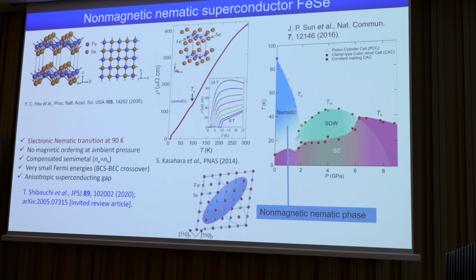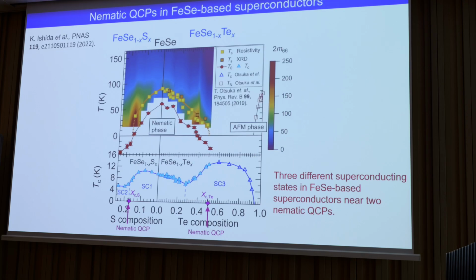But we want to try to understand the interplay between the nematicity and superconductivity. Our next strategy is to use chemical pressure, so we can substitute the selenium site with the isovalent sulfur or tellurium. In this phase diagram we have iron selenium here, with sulfur substitution on the left-hand side and tellurium substitution on the right-hand side. In both cases, we can suppress this nematic transition down to 0 like this, without having any additional magnetic order in this phase diagram, up until you reach the iron tellurium end, where you have a different phase.